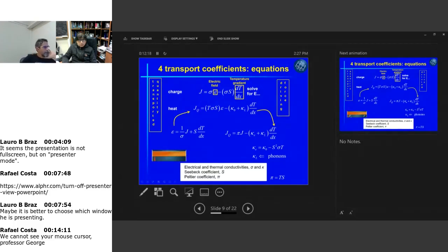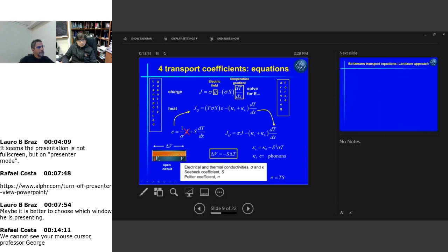So let me show you how you can use these equations to understand what these coefficients are doing. Remember, this is what I showed you in the first slide. You had electrons moving from here to here because of the heat here. They want to be in the cold place. This creates a difference of potential. If you are in an open circuit situation, that's how you measure the Seebeck coefficient. If you have an open circuit, then the charge current is zero in this equation here. So if the charge current is zero, you solve for the voltage, multiply by dx, and integrate, and you obtain that delta V is minus S delta T.